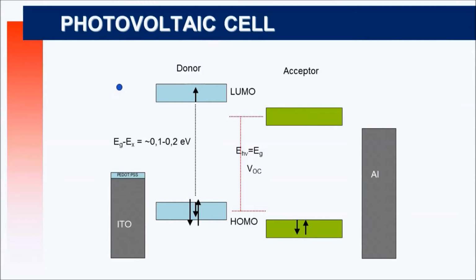So you have absorption from the sun, and then excitation here. But if within the lifetime of this exciton it can travel to the interface here, you will get what we call a photo-induced electron transfer. That has to occur within the lifetime of the exciton, and considering the mobility here, it gives you this size of 10 to 20 nanometers, okay? So if within that time, in the vicinity of this exciton, you have the LUMO of the acceptor here, you will get this photo-induced electron transfer, and therefore you have a positive charge carrier here on the p-type semiconductor, and an n-type or negative charge carrier here on the fullerenes. You have your percolated pathways, you will get photocurrent.